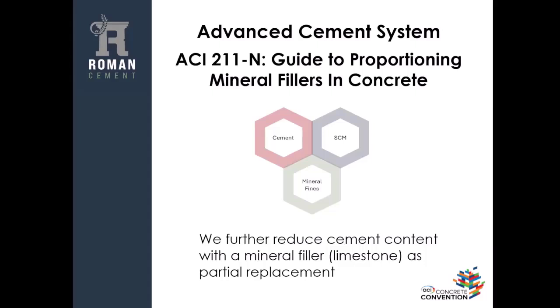Like I said, we've always looked at a ternary blended material. Ideally, the cement and the SCM and the mineral fines wouldn't have the same particle sizes, but in this case, the SCM we used was fly ash in this project, had about the same particle size as the cement, and then our mineral fines were a coarse limestone powder that we found off the shelf. But we were able to use it to reduce cement content significantly and make what we believe would qualify as a low carbon material under 323, but we didn't have the workability issues that you might have if you reduced cement paste dramatically.